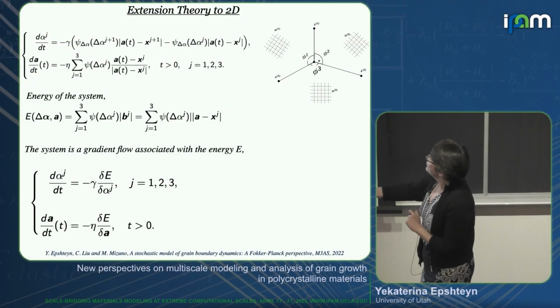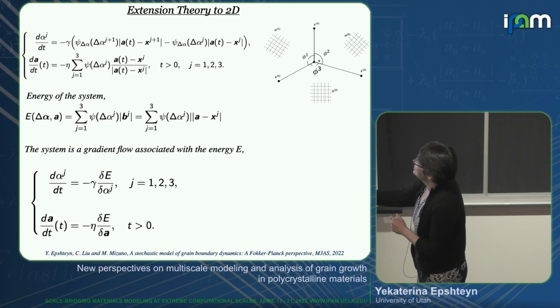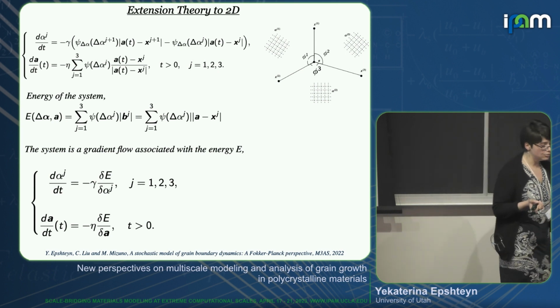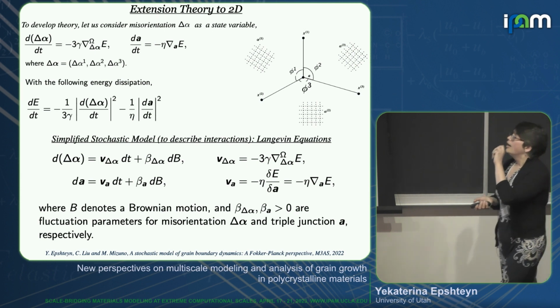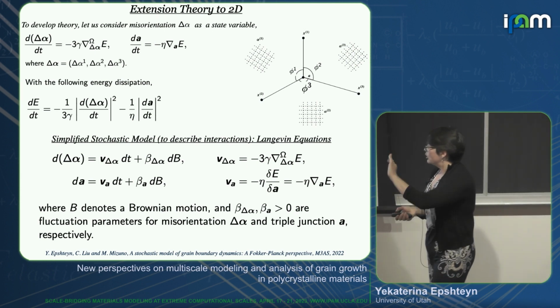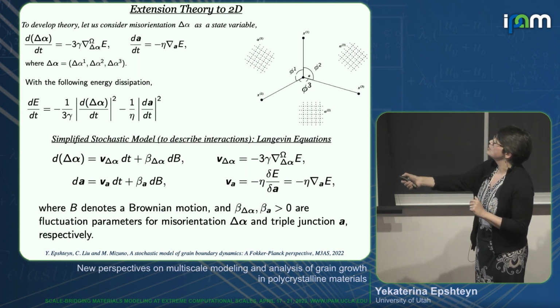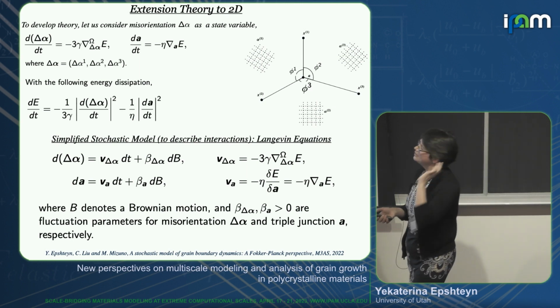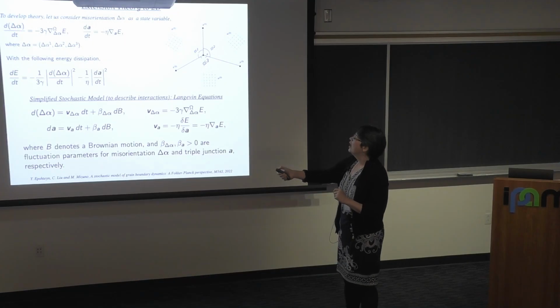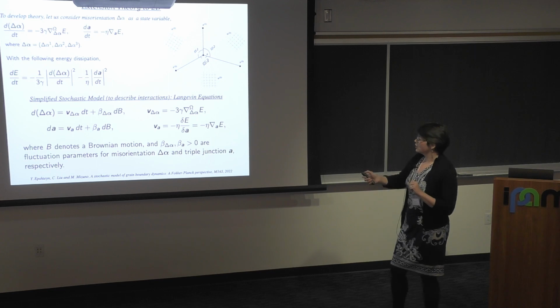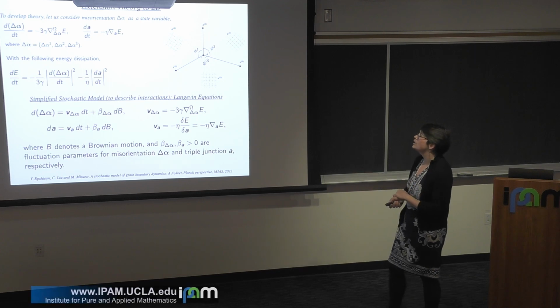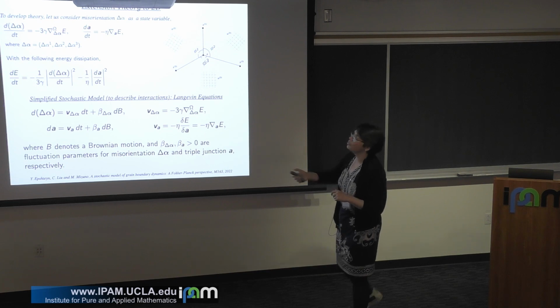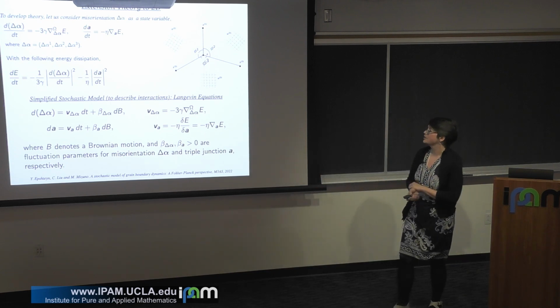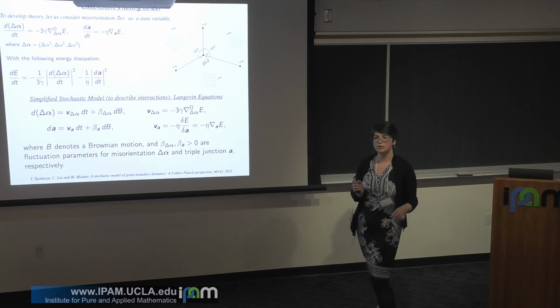So here is this system that I presented earlier, written for a single triple junction and free grain boundaries. It's a gradient flow for triple junction and orientation. But since we're interested really in grain boundary character distribution, which is related to misorientation rather than orientation, we wanted to change our state variable from orientation to misorientation. It's not that hard to do. Again, you can show that it's a gradient flow with respect to misorientation and position of the triple junction. But again, this is for a single triple junction.